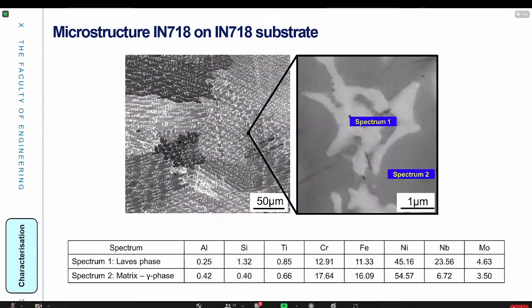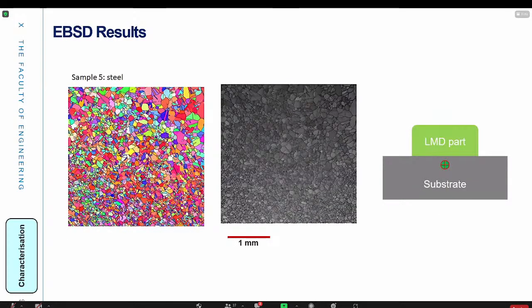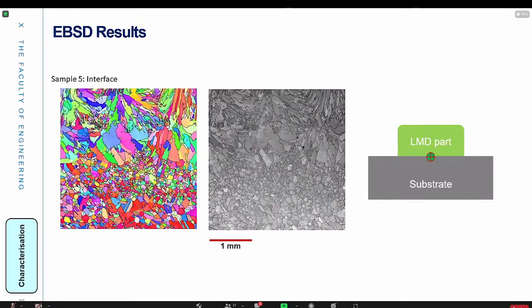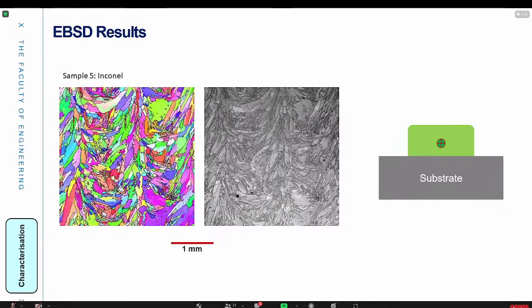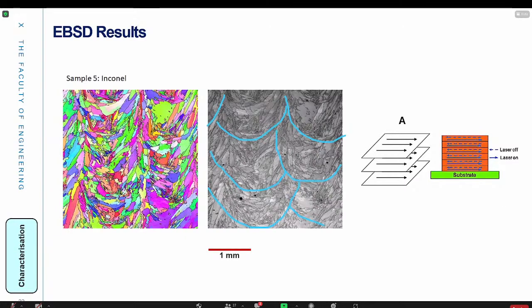And we checked the Laves phase, the matrix gamma phase, and also we checked with the EBSD result on the substrate, and the interface area, where we have a kind of recrystallization, and also we have the columnar grain. Actually, by changing the G and R within the melting pool, we have different microstructure features, including the equiaxed grain near the interface, and elongated grain here, and with different building strategies we can see different passes also.